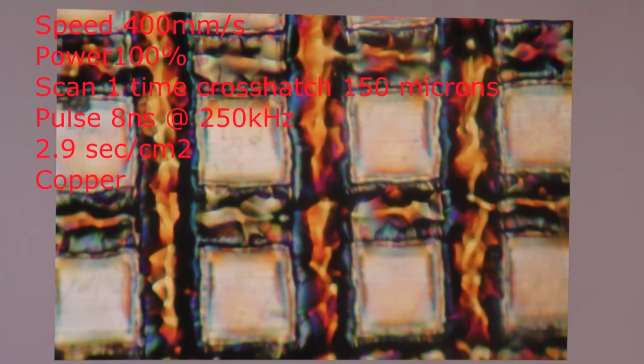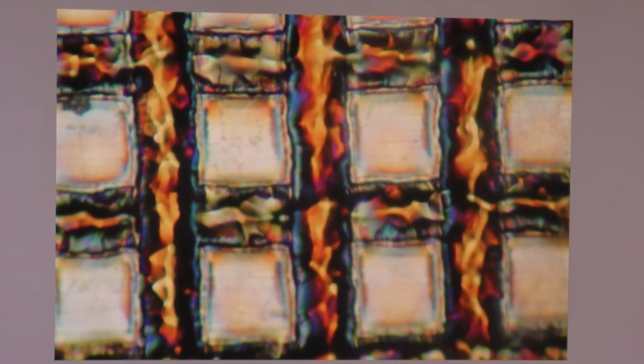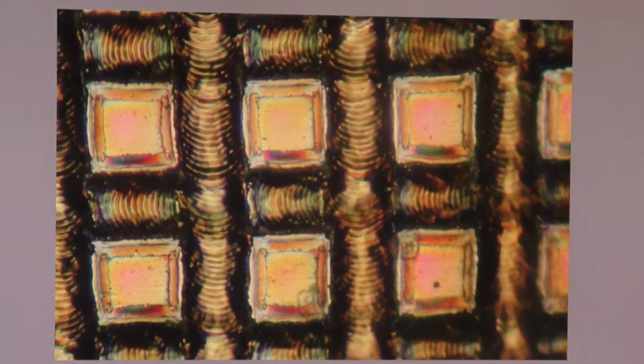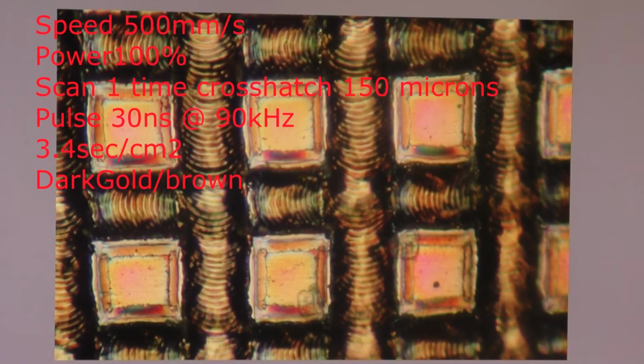So this is exactly the same settings as the previous one, except the speed has been changed from 600 to 400. So in going down to 400, we've actually allowed more pulses per millimetre, and we've had a greater heating effect. So our gold has now changed into a copper colour. And maybe you can see that in the redness of the beam. And that's what's probably causing the effect when it gets to the eye. I absolutely love this one. This is like almost a modern artwork. This actually comes out as a very, very dark gold, almost a brown.